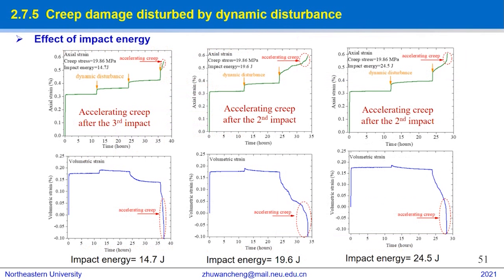The strain and strain rates during the creep impact experiments of rock specimens with different impact energies are shown in this slide. The time to failure shortened from 37.26 hours to 33.68 hours and to 28.20 hours as the impact energy increased from 14.7 joule to 19.6 joule and to 24.5 joule, respectively. Affected by the first dynamic disturbance, all of the axial strain curves showed a sudden increase, a primary decelerating phase, and a steady state phase.